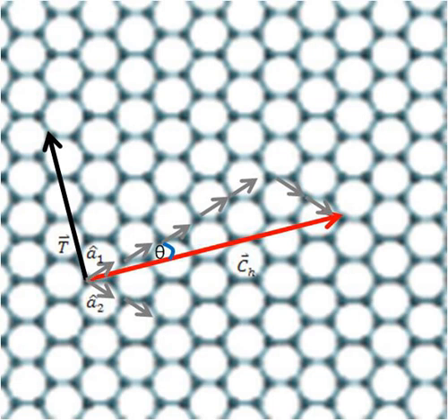The differences in the chiral angle and the diameter cause the differences in the properties of the various carbon nanotubes. For example, it can be shown that an (n, m) carbon nanotube is metallic when n equals m, has a small gap, i.e. semi-metallic, when n minus m equals 3i, where i is an integer, and is semiconducting when n minus m does not equal 3i.